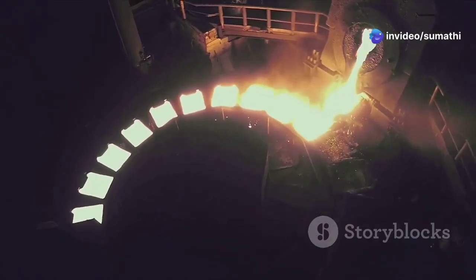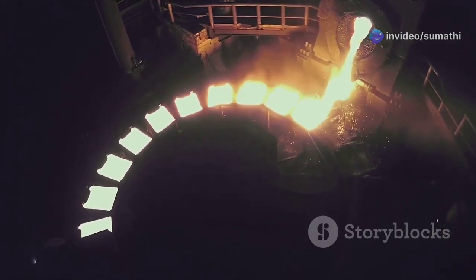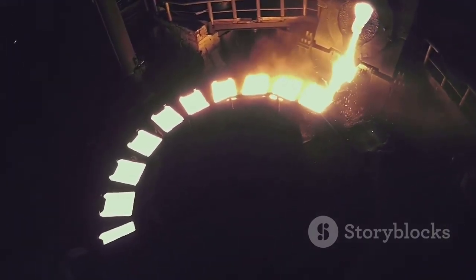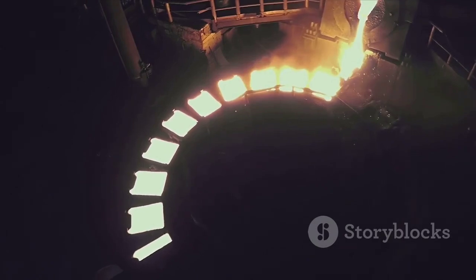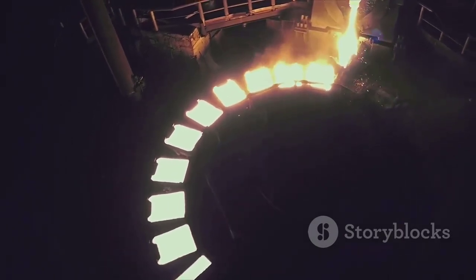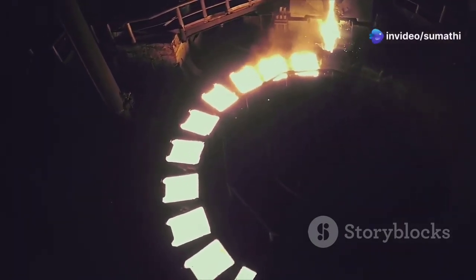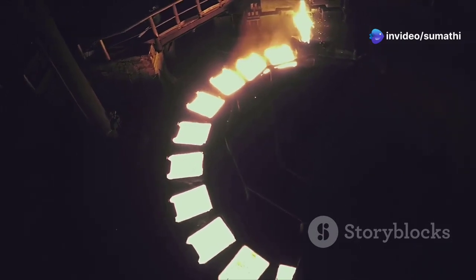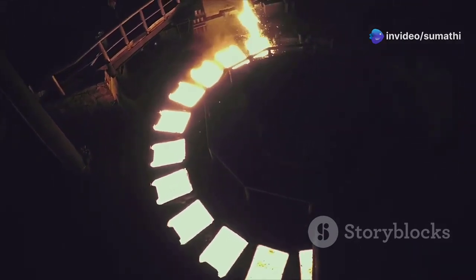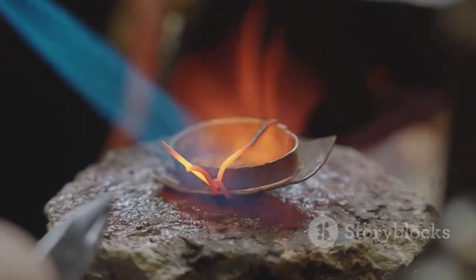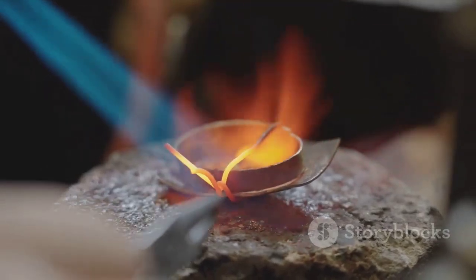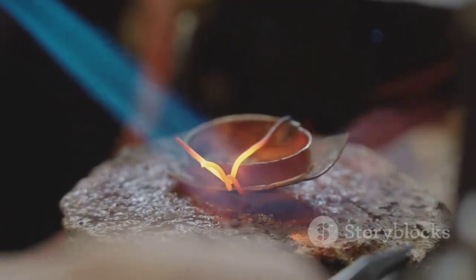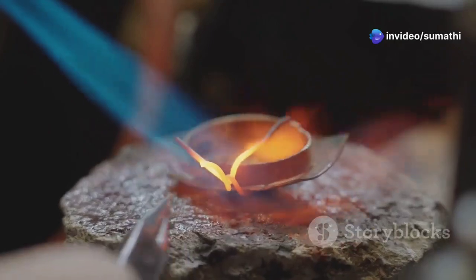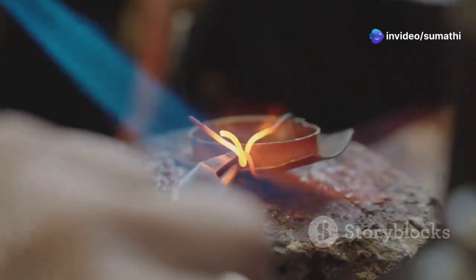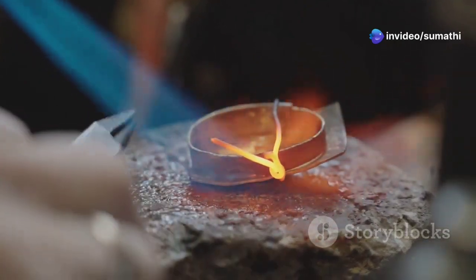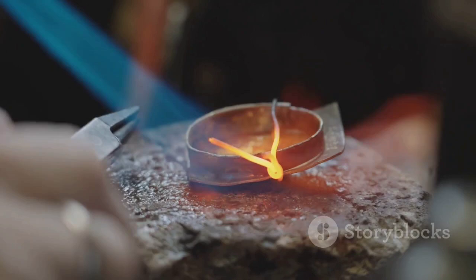Apply heat. If using a furnace, slowly increase the temperature until the gold melts. The melting point of gold is 1064 degrees Celsius, or 1947 degrees Fahrenheit. Gradually increasing the temperature helps to avoid thermal shock, which can crack the crucible. If using a torch, direct the flame at the base of the crucible, moving it in a circular motion to distribute the heat evenly. This technique ensures that the gold heats uniformly, preventing hot spots that could cause uneven melting or damage to the crucible.